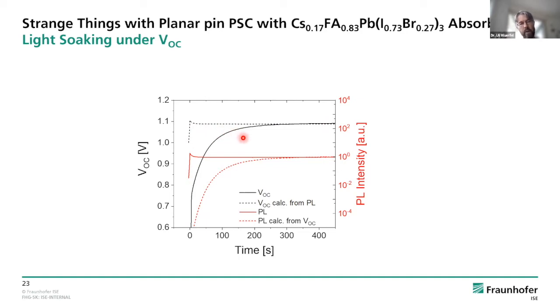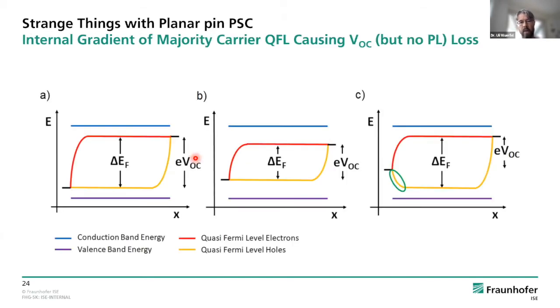And we thought about it, what could be the reason? The high PL intensity means that at this point in time you have a high charge carrier density, but somehow the high charge carrier density does not translate into a high VOC. Why is this so? Here you have 3 different cases. Please look first at the left. This is a good solar cell. It has a large separation of quasi-Fermi levels within the absorber, and the quasi-Fermi levels of the majority, so electrons here and holes here, go straight, and then the elementary charge times VOC is the same as the quasi-Fermi level separation. So this is, let's say, what you want to achieve. This device would then also have a high photoluminescence intensity, and its PL intensity correlates directly with the open circuit voltage.